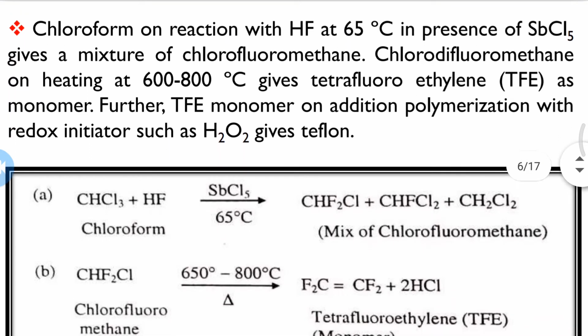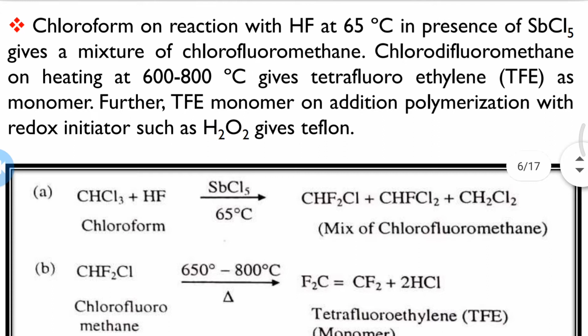So, the preparation of Teflon. Here, chloroform on reaction with hydrofluoric acid, HF, at 65 degrees centigrade in presence of SbCl5 catalyst gives a mixture of chlorofluoromethanes.